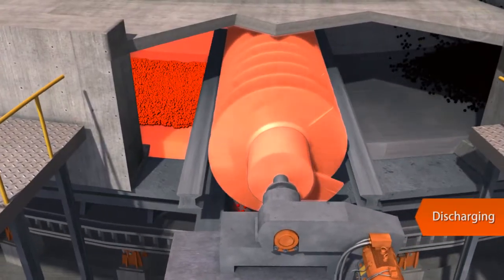Heating with Shenwu's regenerative burner, the carbonaceous pellets can be gradually reduced while going through the preheating zone, middle temperature reduction zone, and high temperature reduction zone by means of controlling the in-furnace temperature and the rotation rate of the hearth. The metallized pellets of approximately 1000 degrees centigrade are then discharged out of the furnace with a specially designed discharging device.